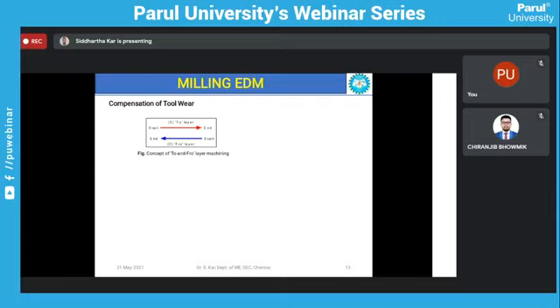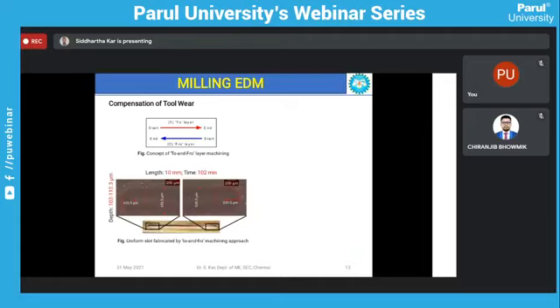So by this technique we can compensate the wear of the tool that is occurring at the initial two layers. So by the fourth layer we are compensating the initial wear that is occurring in the two layers. So by implementing this technique, a uniform slot has been fabricated on a titanium workpiece.